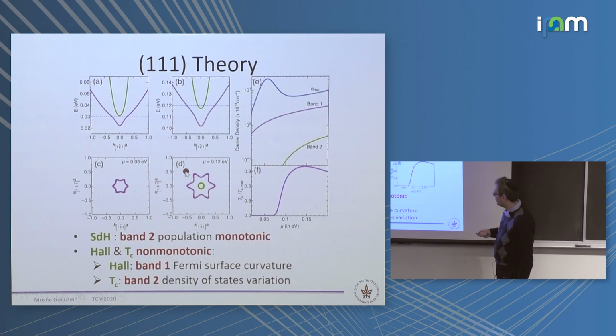And the reason could be simple because of the 6-fold symmetry along this interface. So the Fermi surfaces of band 1 are very much curved, and this curvature means that it has mixed electron and hole features, and this is enough to give rise to enhanced Hall number in some regions of the Fermi energy, like in the experiment.